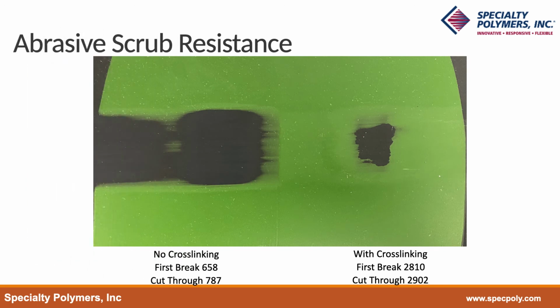The crosslinking also had a very large effect on the abrasive scrub resistance. The paint with the ambient temperature crosslinking had much better scrub than the paint made with the acrylic analog without the crosslinking. This may indicate that the abrasion under foot traffic would be much better for the cross-linked paint.